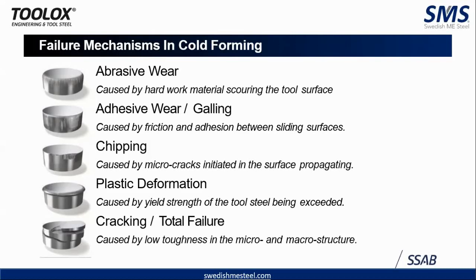If you go from the bottom, if you have the issue of cracking, then you need not worry. Toolox has a guaranteed toughness of 18 joules and an average value of 30. That will help you in addressing the issue of cracking. It has a high yield strength of 1300 MPa, so plastic deformation also has been taken care of. Even if a crack initiates, it will not propagate through the material, thanks to the toughness of the material. And adhesive and abrasive wear can also be taken care of by providing good surface engineering solutions.